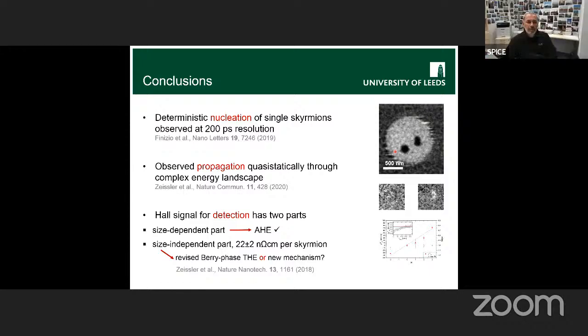Yeah, I think maybe scanning electron microscopy with polarization analysis, SEMPA, can actually be used. Yeah, all of the various quantitative MFM methods, and nitrogen-vacancy center imaging. Usually you're picking out one component of the magnetization, but if you measure again and again, picking out different components, then you can build up the full vector map of your magnetization texture.